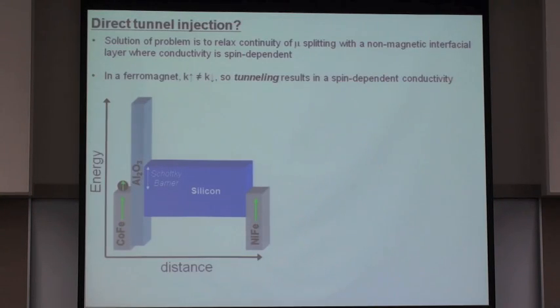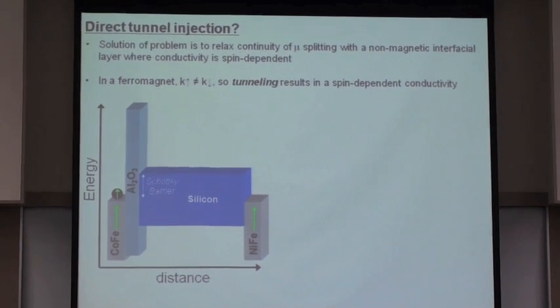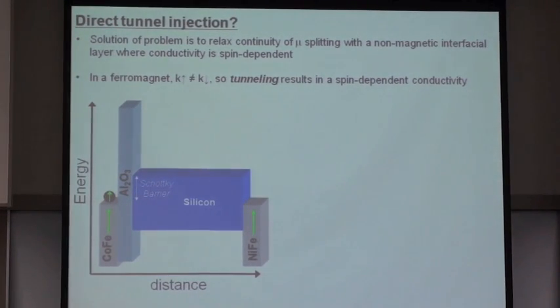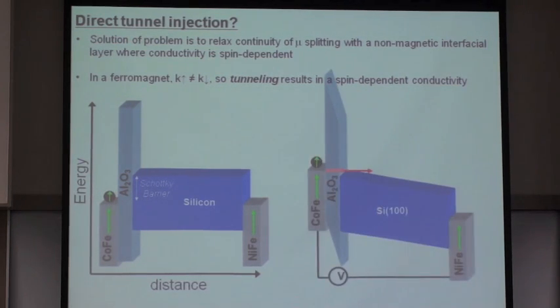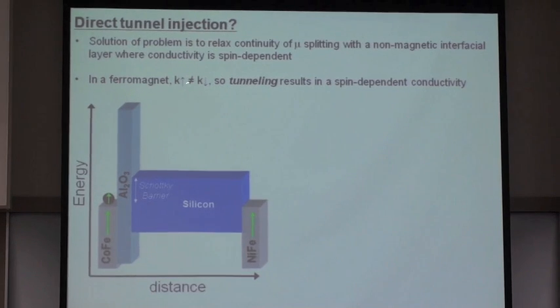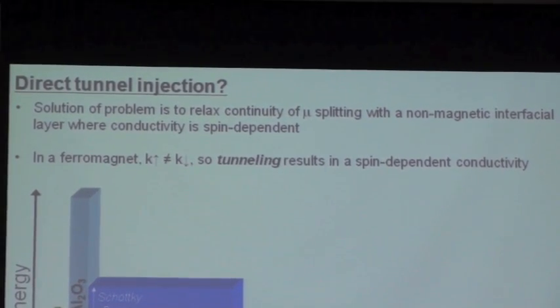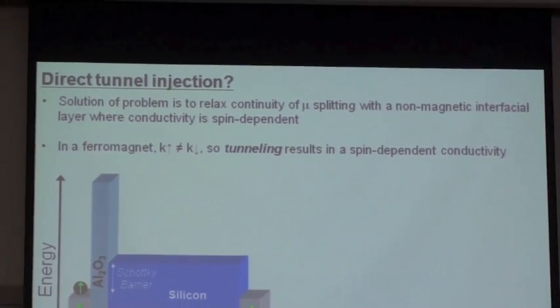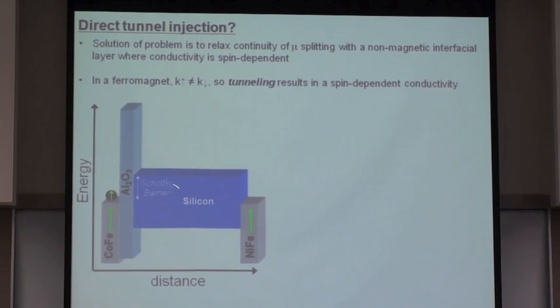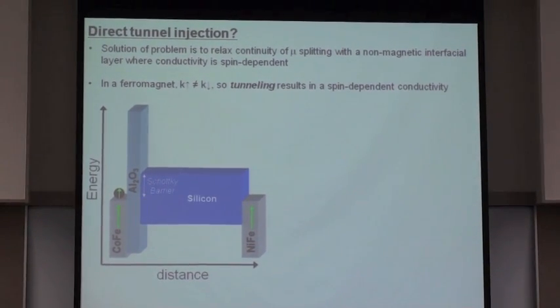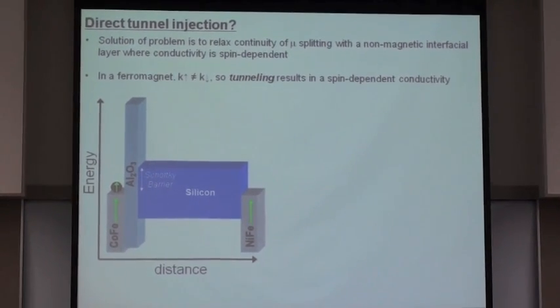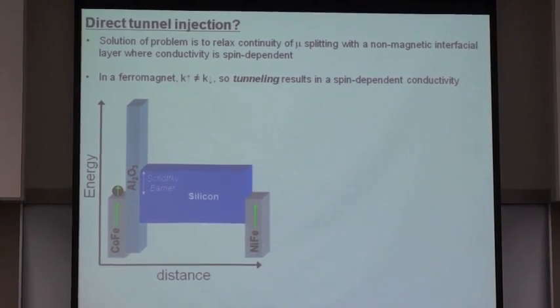Now, the one way to achieve this is through tunneling. It turns out, of course, that the tunneling probability is dependent on the wave number, which is different for spin up and spin down due to the splitting of the band structure in the ferromagnet. And so one might propose, what we have to do is just take our ferromagnet and separate it from our semiconductor by a thin tunnel barrier of just a few nanometers, and then we'll achieve what we wanted.